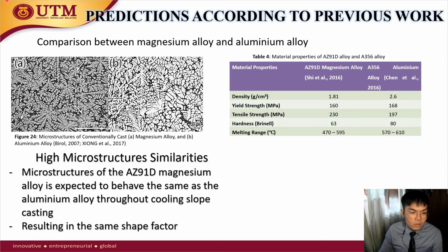It turns out the microstructure of the AZ91D magnesium alloy is expected to behave the same as the aluminum alloy throughout cooling slope casting, and this may result in the same shape factor after cooling slope casting because they have a very similar microstructure, as you can see from figure 24.